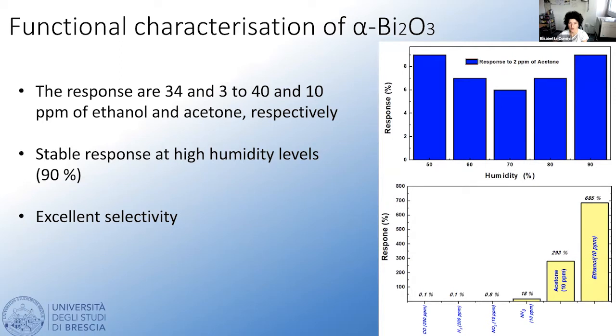And we have also tried how the response is influenced by the humidity. So this is the response of bismuth oxide nanowires towards 2 ppm of acetone over different values of humidity from 50 to 90%. And we can see that the variation in percentage is relatively low. So we have also tested other compounds to see the selectivity of bismuth oxide nanowires.